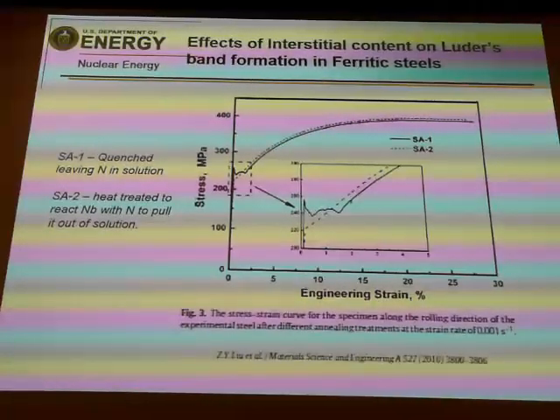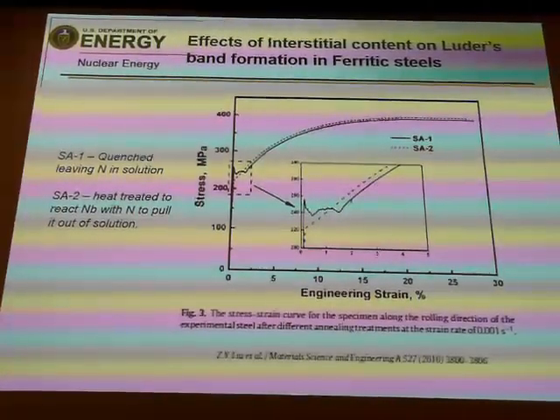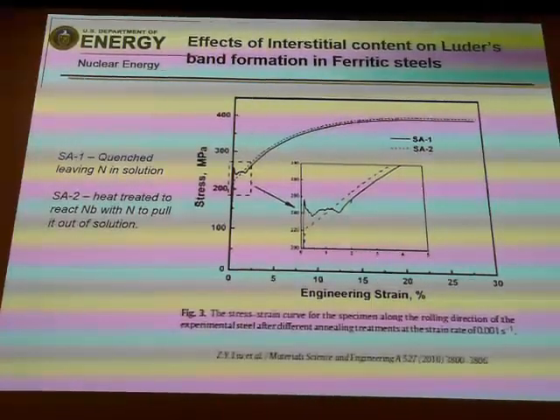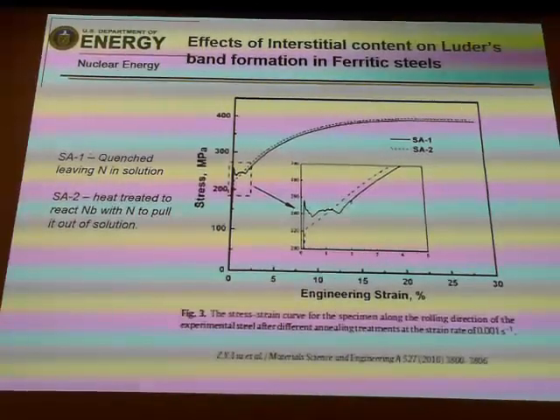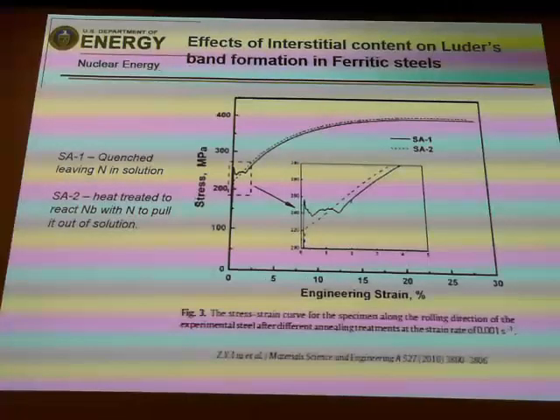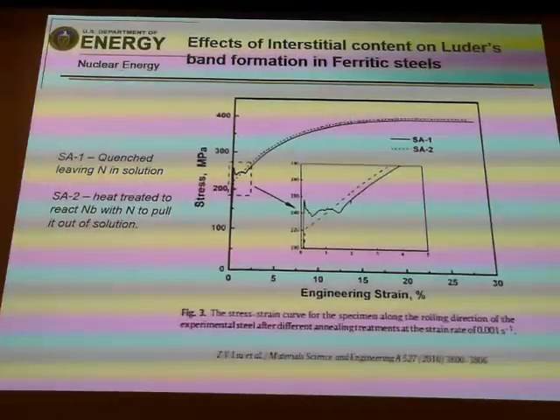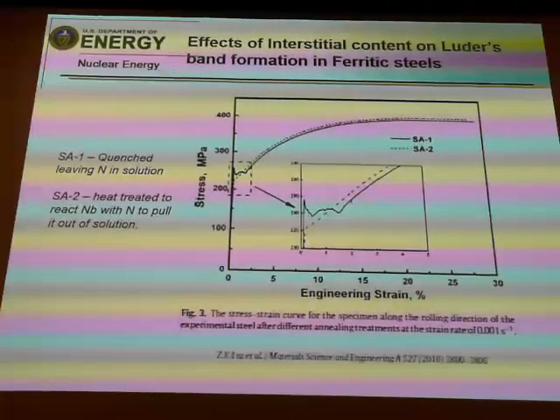This is just a typical ferritic steel, exactly the same alloy, one where they heat treated it and quenched it to leave nitrogen in solution, and there you see strong Lüders band formation and load drops, or localized deformation, at the beginning of deformation of that material. The other was heat treated and the niobium was reacted with the nitrogen to pull it out of solution, and you can see you completely remove that Lüders band formation. So by going to a low nitrogen alloy, you can reduce localized deformation in a ferritic steel.